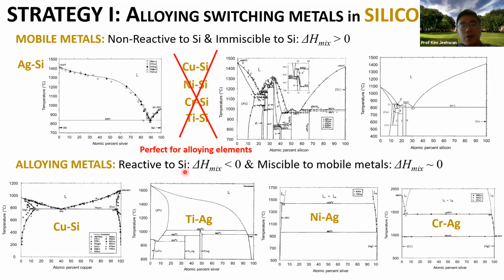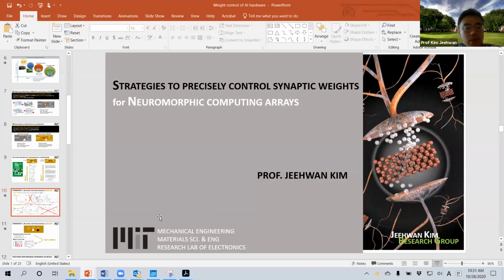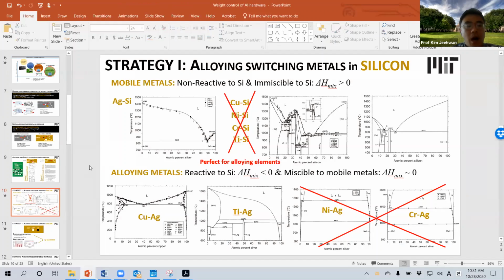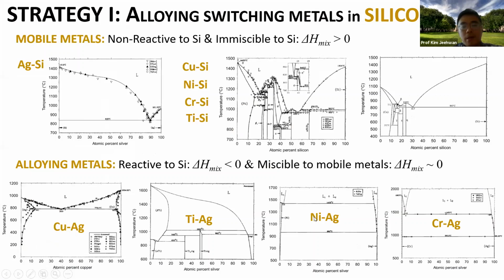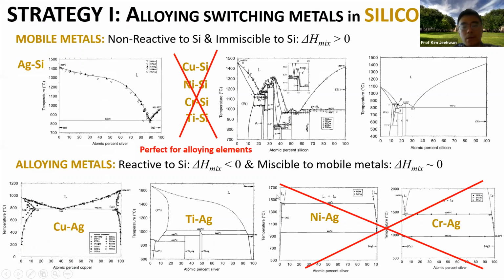Not only that, this metal has to be miscible with the mobile atoms, meaning that this alloying metal needs to like silicon. At the same time, this alloying metal needs to like the silver as well. As you can see here, this is a typo. Sorry, this is a typo. As you can see here, copper and titanium like each other. There's a solid solubility. However, nickel silver and chrome silver, they do not like each other because there's no solid solubility. So this nickel and chrome cannot be the alloying metals, but thermodynamically, copper and Ti can be good interface material.